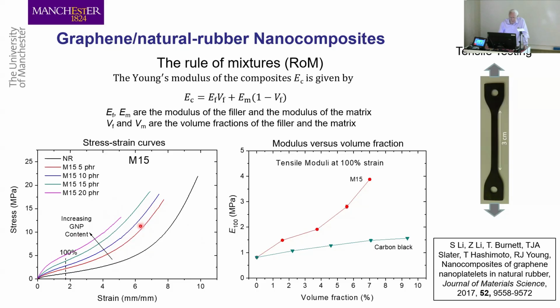So that's quite interesting. We can try and analyze the behavior just using a simple rule of mixtures, which tells you essentially how the graphene is behaving. The rule of mixtures says the modulus of the composite should be the modulus of the filler times the volume fraction, plus the modulus of the matrix times its volume fraction. So if you plot the modulus of the material against the volume fraction of filler, compare it, say, with carbon black, way down here, doesn't do a great deal, but with the M15 nanoplatelets we used, we get a slope, a straight line roughly.